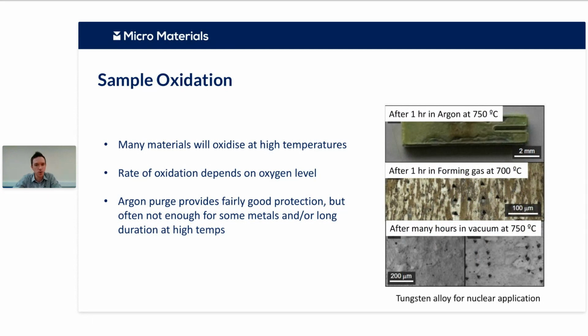or if we want to perform long duration tests. You can see in these pictures on the right here, we have a tungsten alloy, a metal that very rapidly oxidizes at high temperatures. Even in an argon environment, after 1 hour at 750 degrees C, we see extensive oxidation of the surface. After 1 hour in forming gas at 700 degrees, it's not as bad, but we're still seeing areas of oxidation on the surface. However, in a high vacuum environment, as you can see here on the bottom, this is at 750 degrees, after many, many hours, probably more than 12 hours at least, we don't see any visible signs of oxidation.